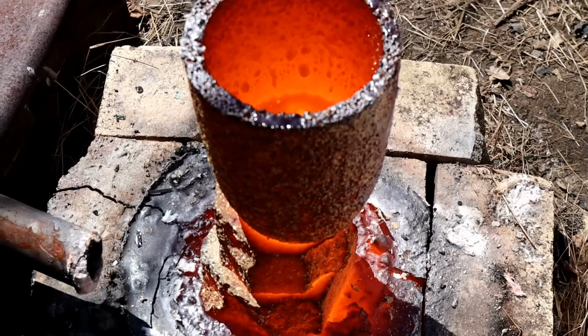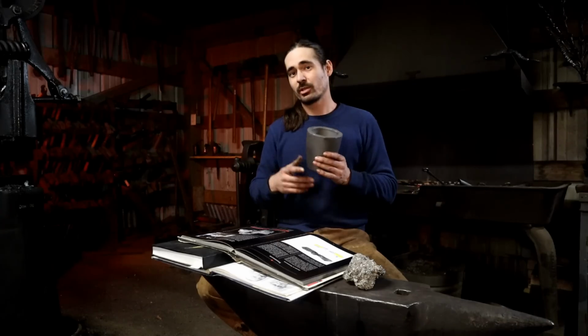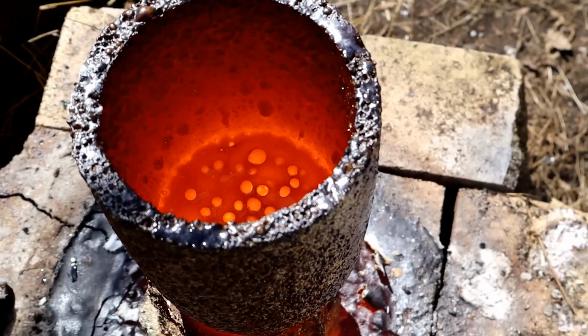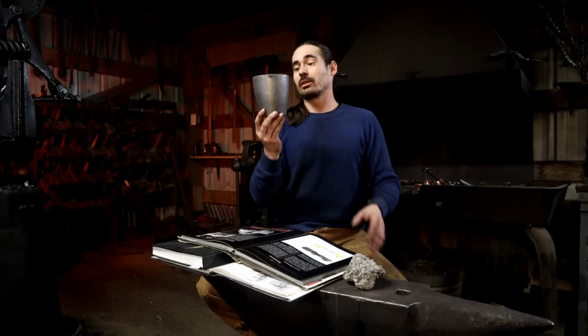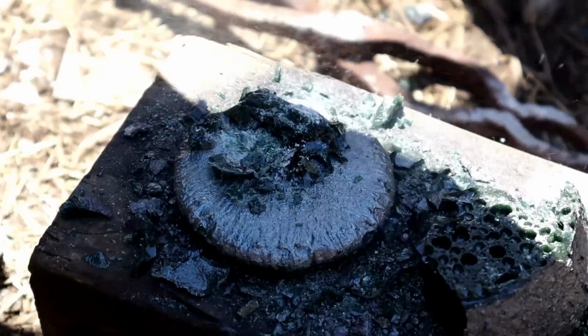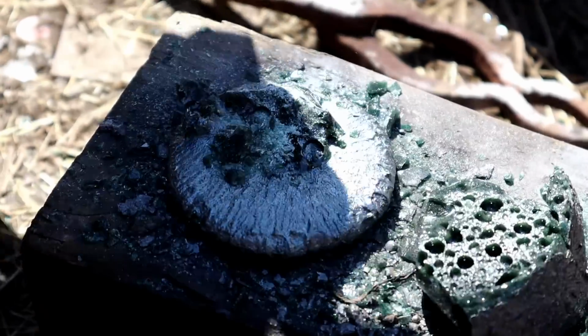So my furnace can be a big fire with a blower underneath. It could look very much like a bloomery smelter, except my crucible is enclosed, so it does not allow my stuff to escape. Once the material inside is molten, what happens is very much similar to the standard bloomery smelter, except it is enclosed, so my stuff doesn't float away. The hematite starts interacting with the carbon in the charcoal. The slag melts out and moves to the surface. It will end up looking like glass, and the carbon gets absorbed by the iron, producing a steel puck. That steel puck is very solid inside and has no slag, as the slag moved to the top previously. It tends to be very high carbon.